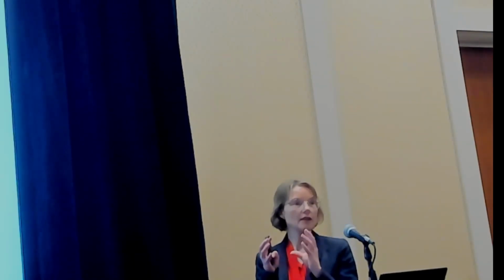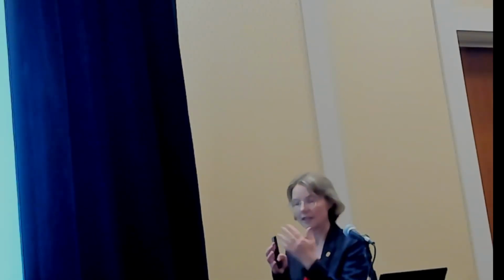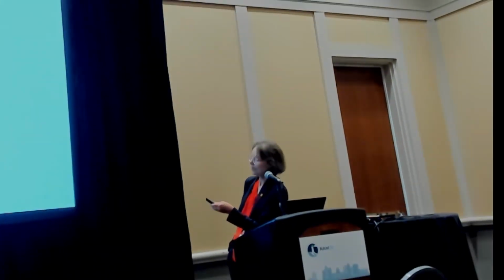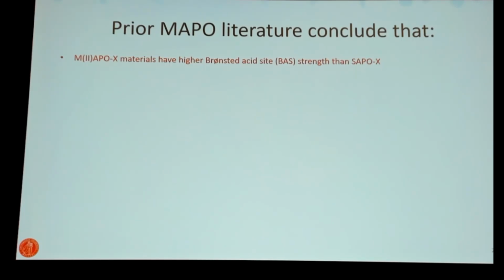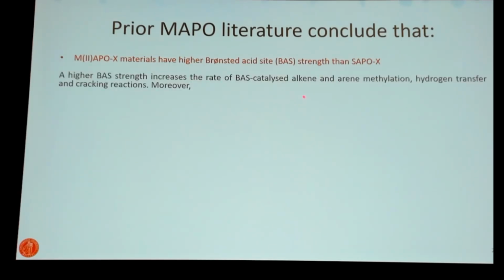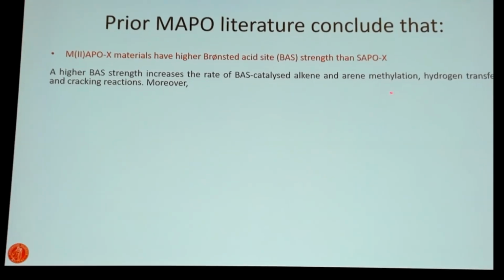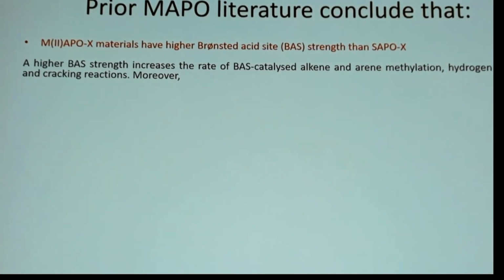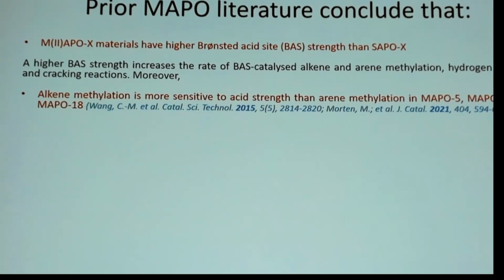Of course, with this cavity window structure, we cannot really study the reaction mechanism, because what is diluted out of the crystal is not representative of what is inside. And so I just cite to you some previous work that has been done. We know that if we have a higher acid strength, then we will have some impact. Typically, we increase the rate of all those Brønsted acid site catalyzed reactions like alkene and arene methylation, hydrogen transfer reactions, and cracking reactions.